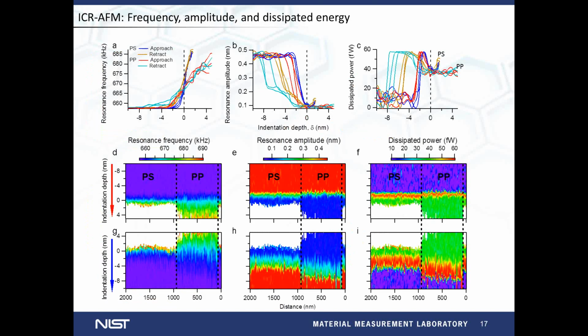An analysis can also be made in terms of depth dependence of the dissipated power. Here on top are shown individual curves of depth dependence of resonance frequency, amplitude, and dissipated power. On the bottom are plotted the same quantities along a scan line. So we have a colorful, nice distinction between the two materials, how they respond during contact formation and contact breaking. If we look at the dissipated power curves here with red and blue, we observe comparable maxima in the dissipated power just before the contact is formed, but once the contact is formed, we see a distinct behavior with almost constant dissipated power on polypropylene and a monotonic increase in polystyrene.